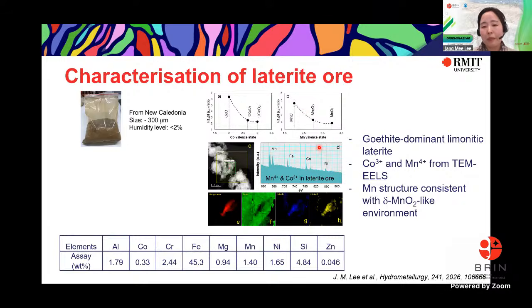Because through the XPS, manganese can be detected, but cobalt is a really tiny amount, and XPS is sort of a bulk characterization, so it cannot be detected through the XPS to figure out the oxidation state. So that's the reason why I chose this TEY characterization to locally figure out the oxidation state of the cobalt. Through this TEY characterization, we could figure out cobalt exists as +3 and manganese exists as +4 mainly. And through the XRD, the main phase is the goethite crystal structure, iron oxyhydroxide, and the secondary phase was the quartz phase, silica.